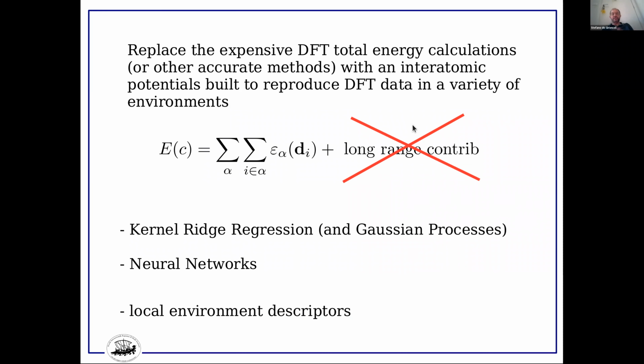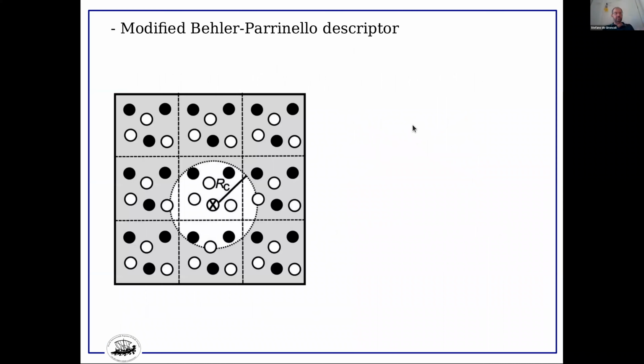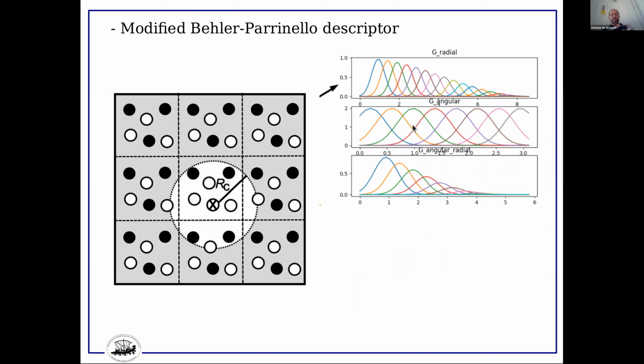And all these methods, whether it is the Gaussian processes or a neural network potential, are based on this decomposition, at least in their original formulation. They are based on this atomic total energy decomposition in atomic contributions, and on the description of what this local environment is. So we used the modified Behler-Parrinello descriptor, in which basically to each atom you attach, you build a sphere around each atom, and then you count how many atoms are at a given distance, and then you count how many pairs of atoms are at different distances and at different angles. And so from that, you basically build a population, a histogram, of a kind of